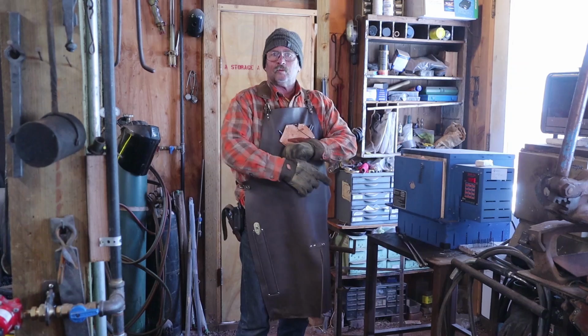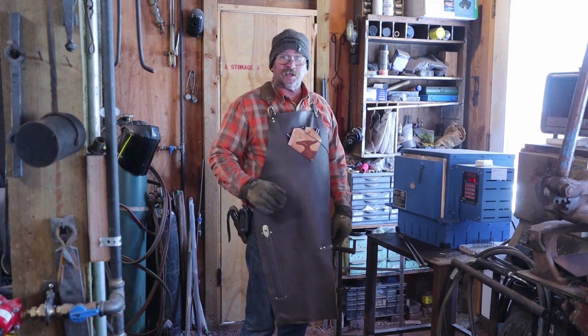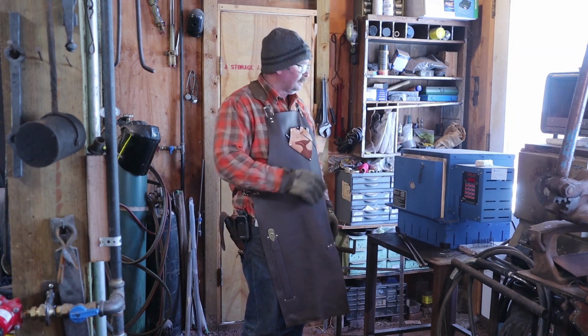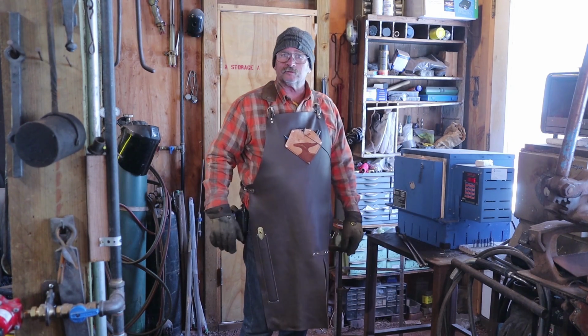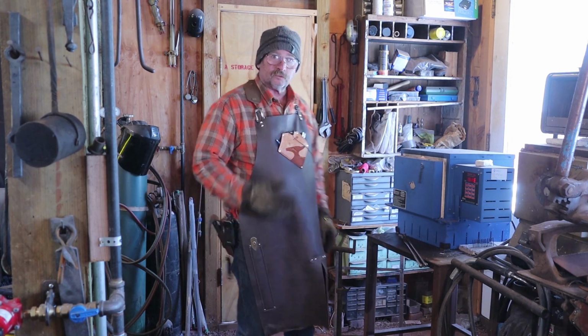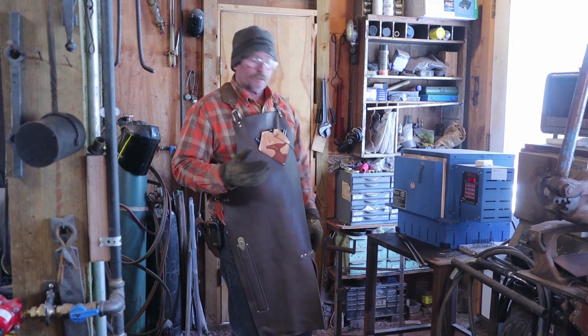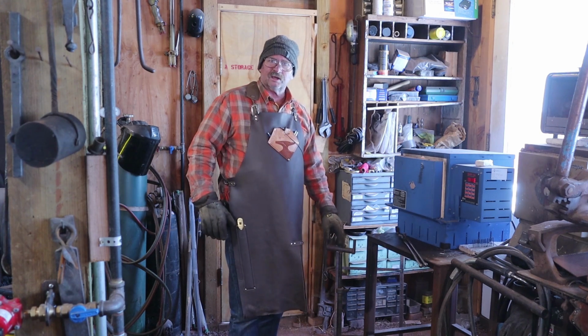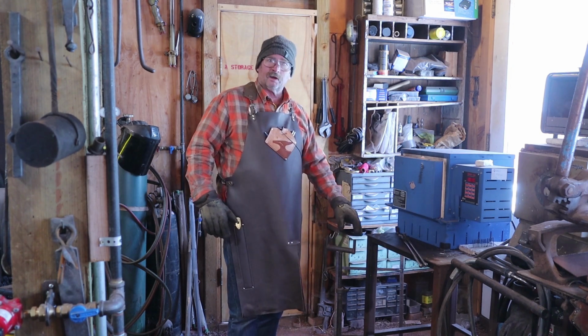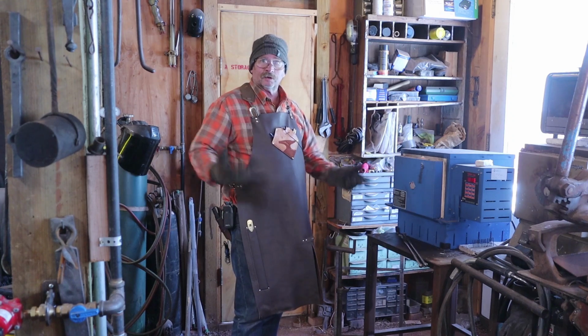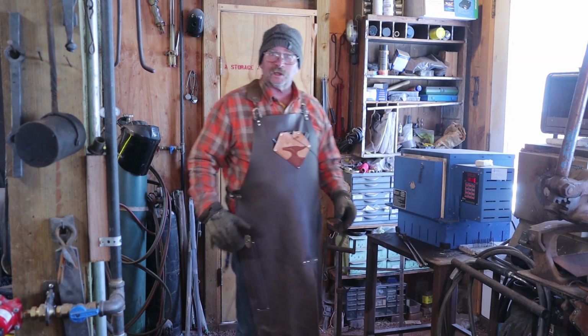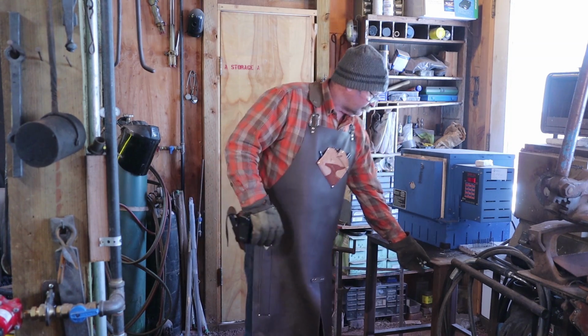So I'm going to bring these up to heat, I'm going to air cool them, and then it'll be time to temper them. Well, it's been about 2 hours coming up to heat for our two hammerheads. They're well into their 20-minute soak period. That's just about done, so it's time to bring these out. I'm going to let them air cool. I've got a little work stand here with a couple of prongs on it that I can set the eye of the hammer down. That way air circulates all the way around the hammerhead. Should cool nice and evenly.